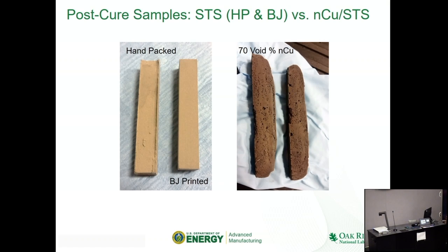So this 70% void space is the targeted void space. This is the void space we were targeting to fill. So here's my box, right? If 60% of this is filled and 40% is empty, I targeted 70% of the 40% to fill with nanoparticles. And this is what I got. But yes, this is what was printed.